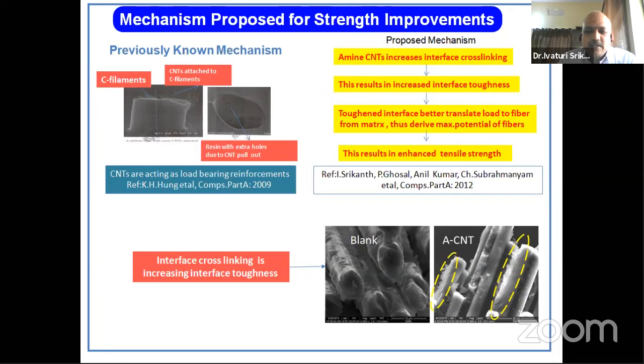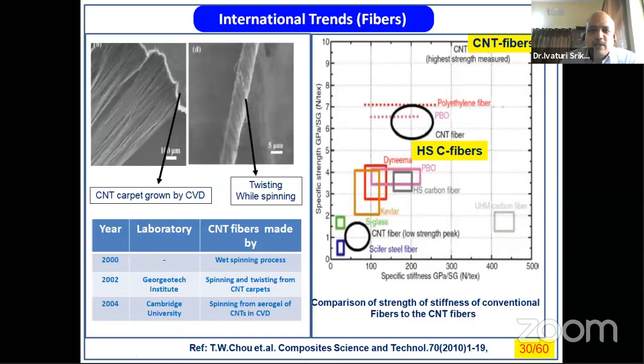Similarly, as long as you are using the nanotubes having 80 GPa or say 40 GPa strength with an 8 GPa or 5 GPa strength carbon fiber, the moment carbon fiber fails, the composite fails, because any failure, any fracture, any crack at one zone will easily propagate to the other zone. So as long as you are using the nanotubes along with the conventional carbon fibers as an additional reinforcement, you can never get a very good improvement in mechanical properties.